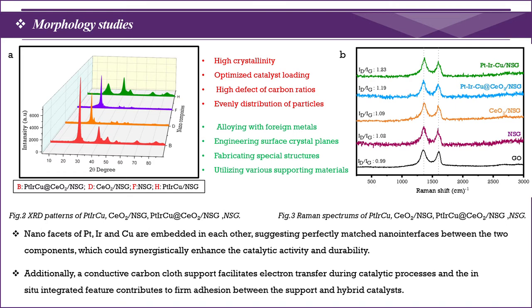In the results and discussion part, crystal orientation and carbon defect development were evaluated by XRD and Raman analysis, shown in figures A and B. The ultimate catalyst — Pt-Iridium-Copper cerium oxide doped on nitrogen-sulfur graphene oxide — possesses high crystallinity compared to parent and comparison materials, and the graphene D/G impact increases gradually in the Raman analysis for each material.